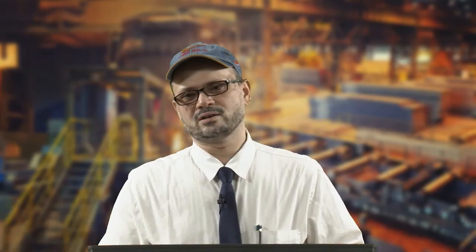You can work with only one caster, but that does not lead to a very high-productivity system since you get only one billet or slab at a time. With a multiple-strand tundish — where the tundish has different outlets — you can have four molds and four products coming out simultaneously. This economizes the process: in the same time it takes to produce one part, you can get four. The cost is also reduced because with one tundish lining you are getting multiple products, making the multi-strand tundish more beneficial.